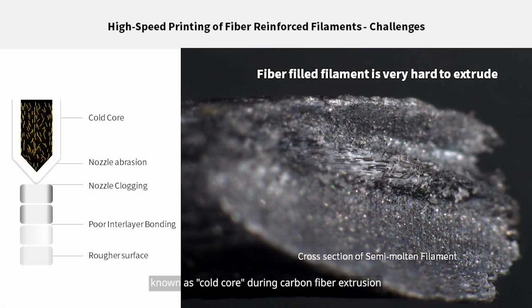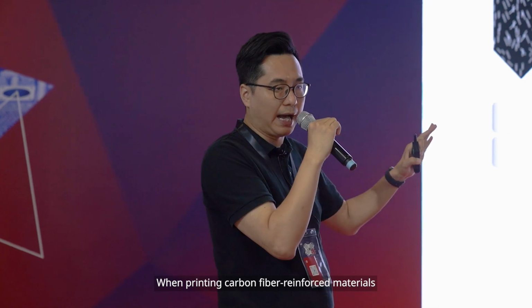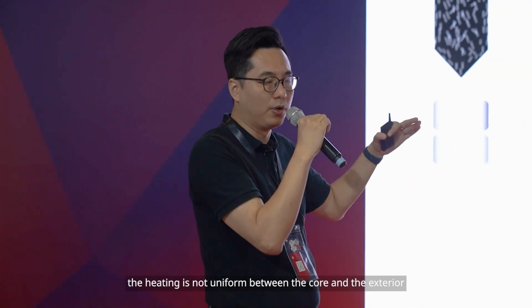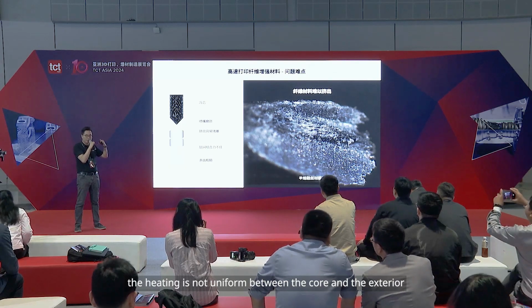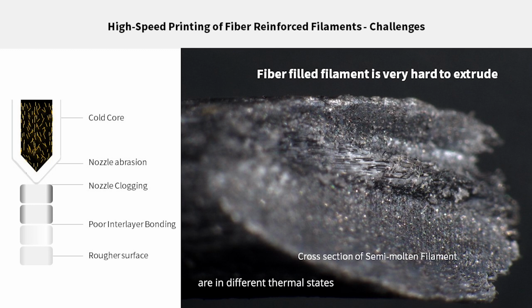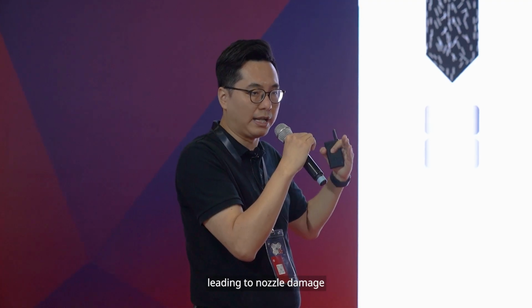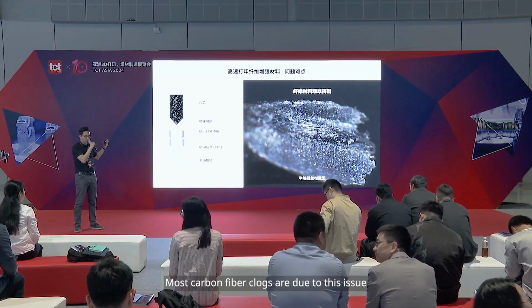This is the condition known as cold core during carbon fiber extrusion. When printing carbon fiber reinforced materials, the heating is not uniform between the core and the exterior. As a result, the core and outer carbon fibers are in different thermal states, with the core remaining at a lower temperature. This discrepancy causes internal carbon fibers to extrude at lower temperatures, leading to nozzle damage. Most carbon fiber clogs are due to this issue.